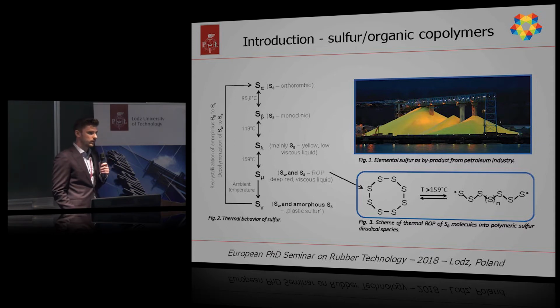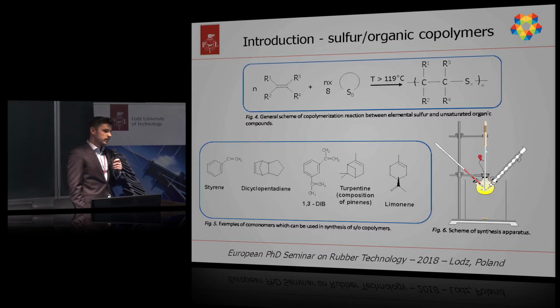But when we now quickly quench the polymerization mixture, we obtain something like plastic sulfur, which is a mixture of polymeric sulfur and sulfur in form of 8-member rings. But polymeric sulfur is unstable and quickly recombines at ambient temperature to monomeric form, so its stabilization is crucial to obtain any useful product. And we can stabilize polymeric sulfur during polymerization process by copolymerization of sulfur with unsaturated organic species like, for example, styrene, dicyclopentadiene, turpentine, or limonene, because the thermally generated diradicals during heating sulfur are very reactive with unsaturated bonds.